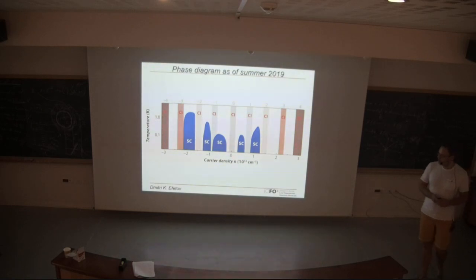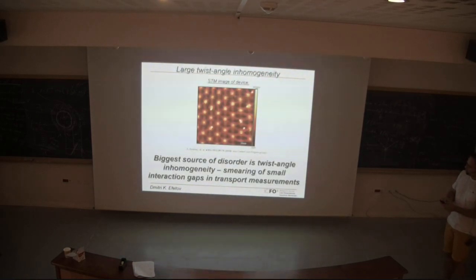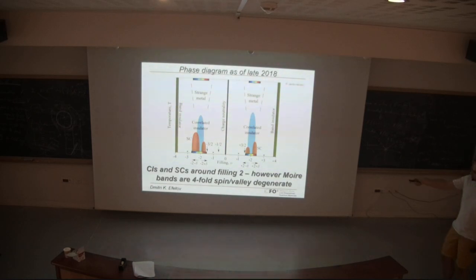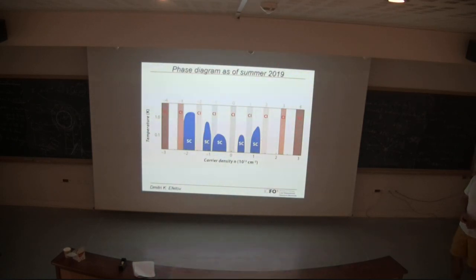I guess what our study adds to the conversation is that it fills up the other integers here, and we can position the same phase diagram at these locations. We get a phase diagram which now has a correlated insulating state for every integer. Also at charge neutrality, at filling 0, we observe a gap, and we think it's a correlated state here too. And superconductivity, as you can see, arises in proximity to many of those correlated states.